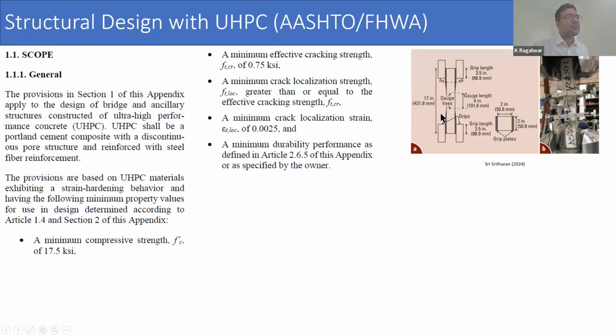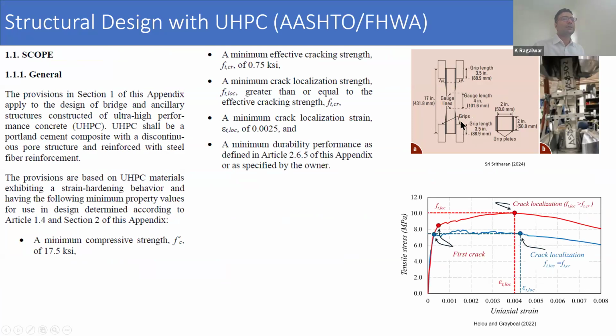So this is a standard setup for performing a uniaxial tensile test. Basically, it's conducted on a prism which is 2 inch by 2 inch, and the length of the specimen is 17 inches. Those are gripped on either ends, and then you subject that to tensile loading. So we can see that there are usually two types of curves. After the first crack, either it maintains that stress and then crack localization occurs, and we can see that stress at crack localization is almost equal to stress at cracking, whereas on the red curve, another specimen, we can see that crack localization is higher than the first cracking.